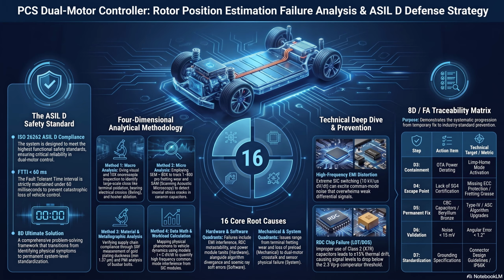Right, going back to the EDX, finding oxygen spikes inside the sealed housing. Yeah. A high-performance vehicle chassis experiences intense modal frequencies. This high-frequency vibration forces the mating surfaces of the electrical pins to slide against each other. But only by like 1 to 200 microns, right? Exactly. It is an almost imperceptible movement. But over millions of cycles, the shear forces at the microscopic asperities, the tiny peaks and valleys of the metal surface, tear the protective gold plating completely off. Once the base metal is exposed and it oxidizes, the contact resistance skyrockets. We're talking going from a nominal 5 milliohms to well over 100 milliohms.